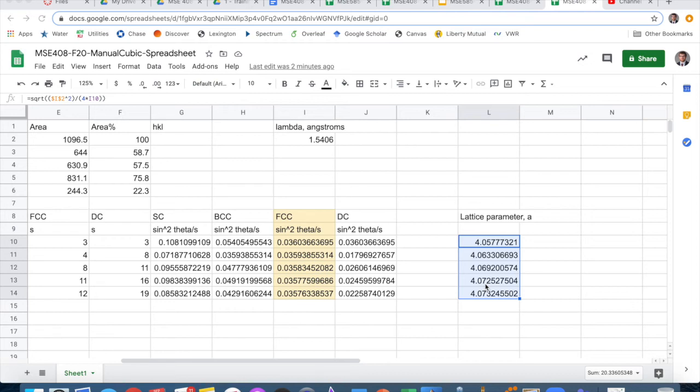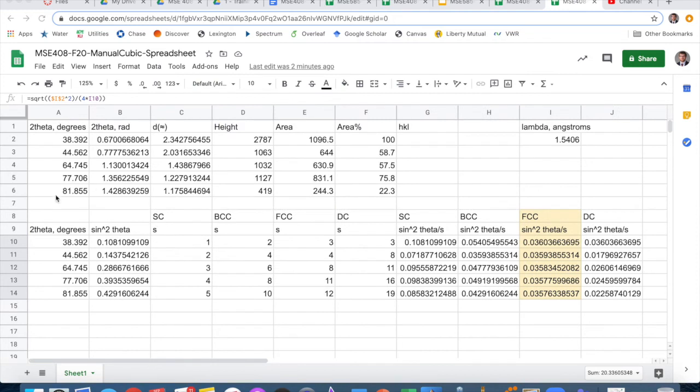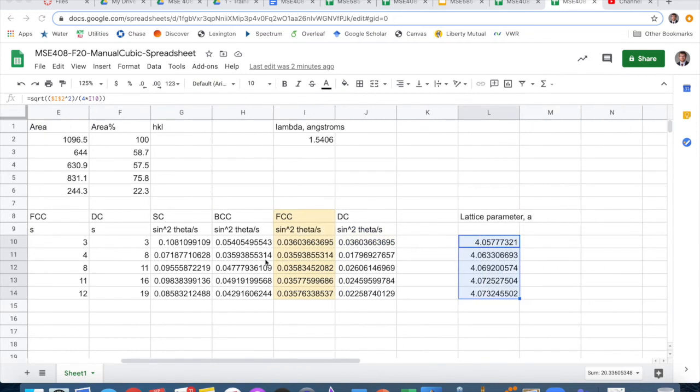So when you're looking at the peaks, and this is something you'll see in the peak fitting videos, those peaks at the higher 2 theta values, so if you go back here, these are closer to 90, tend to be much more broad, and so they tend to give you more reliable values of the lattice parameter. So in this, I would say that the later ones are more accurate than the early ones. So I wouldn't necessarily just take an average or take the first peak. I would probably lean towards one of these later ones and say that our value is close to